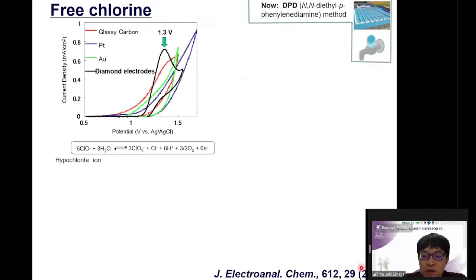Actually, in 2008, a very long time ago, we reported the first example showing the detection of free chlorine. As you can see, when the conventional electrodes, glassy carbon, platinum, and gold, are used, the oxygen evolution is observed at around 1.2 or 1.3 volts. So the detection of chlorine oxidation is very difficult, overlapped here.